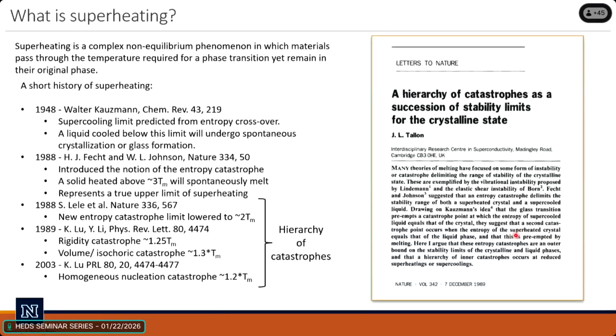And then could you just go through the reasoning for why you can get so highly superheated in this specific experiment? Yeah, so a lot of the melting catastrophes at the lower temperatures, like these ones right here, are time-based. They require some time to happen. Like homogeneous nucleation, you need to be able to nucleate voids in the sample in order to melt. That takes some time. And so if you do something really quickly, you can very easily bypass all of these right here.